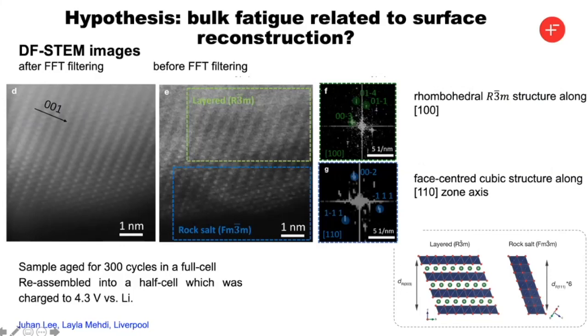So then the question is, what was the relationship with surface reconstruction? And so of course the surface reconstruction of these layered materials to form rock salts on the surface. So this is showing now work of Juhan Lee and Layla from Liverpool, looking at the electron microscopy, the STEM images of the same materials, where you see the classic layered materials moving into the bulk, but then a rock salt cubic structure on the surface.